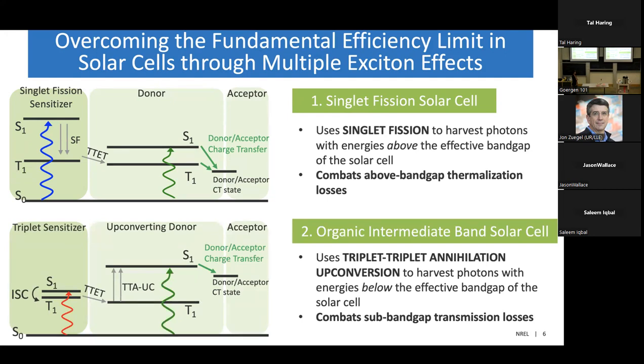Again, we have the classic donor acceptor configuration for the solar cell, but now one of the layers, in this case the donor, is able to perform triplet-triplet annihilation upconversion. And we're adding an additional component here, a triplet sensitizer that can absorb low energy red photons, perform intersystem crossing to transmit triplets into our upconverting layer, all right? So now, in addition to the green photons that this normal solar cell can absorb, by adding this upconversion process, we're able to take advantage of some low energy red photons that previously would have been transmitted. All right, so both of these types of solar cells give us ways of combating both the thermalization losses and the transmission losses that conventional solar cells would experience.